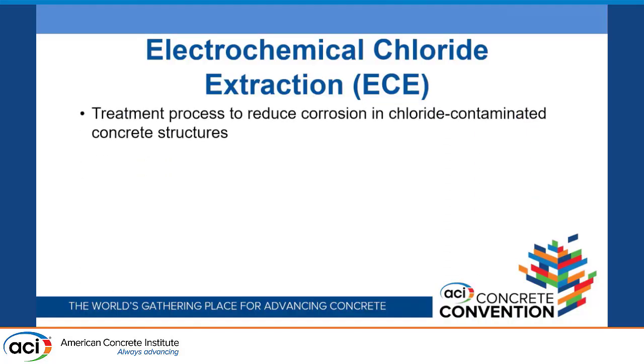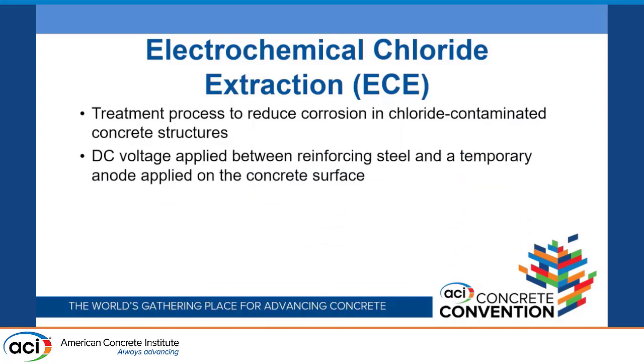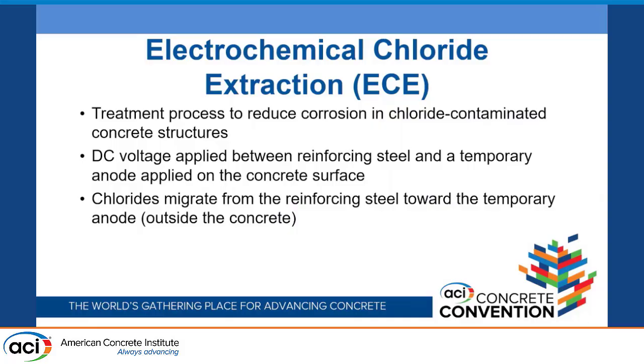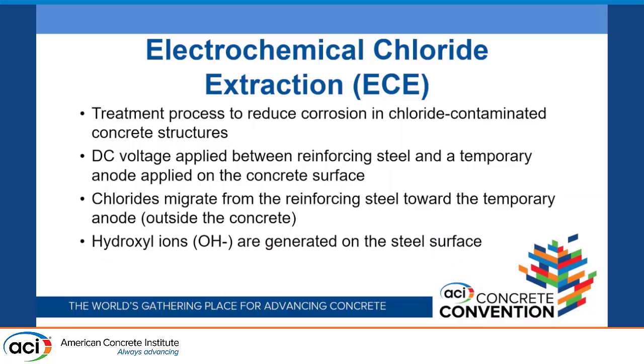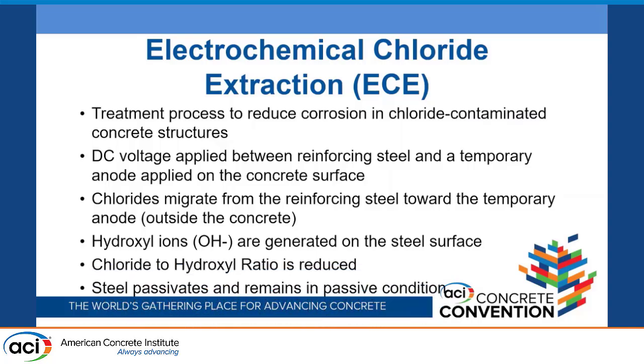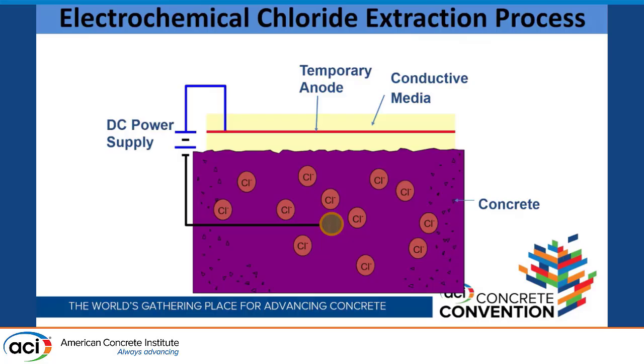So what is electrochemical chloride extraction? It's a process to treat reinforced concrete structures for the purpose of reducing corrosion. You apply a DC current to the structure, similar to impressed current cathodic protection, but it's only applied temporarily, but at a much higher level. And by doing that, you essentially migrate chlorides away from the steel and towards the surface, and a portion of them at least go outside the concrete. And that process also generates hydroxyl around the rebar, so it generates a more passive condition as a result of the chloride to hydroxyl ratio being reduced. That's essentially the process.